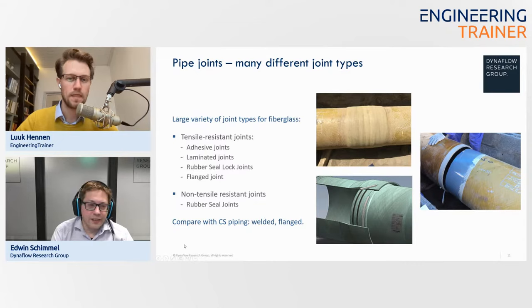Yeah, indeed, the ISO 14692 covers all the qualification really well. It's intended especially for large plants where the reliability of the piping is critical. For a cooling water system, if you have one leak, the whole refinery is down, for example. So the ISO 14692 covers all the qualification well. In the end, it refers to all the standards for the complete test program. So most importantly, you do long-term testing. You start with a series of tests at different durations, with the longest test being around 10,000 hours. That is around 1 year.